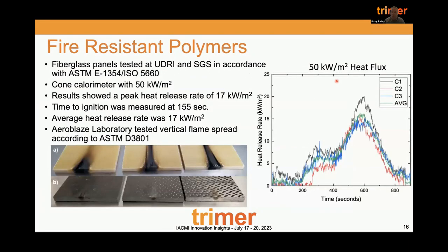If you look at more ASTM level testing, on the right, this is a 50 kilowatt per meter squared cone calorimetry test. It's an ASTM E1354 test. These values, this is with fiberglass, are extremely low. The green line is the average. And these are about a little over a third of what would be required for a Navy submarine. There's currently no material that'll meet that spec. So extremely good fire performance. And these are some vertical flame spreads showing essentially no flame spread, especially in the carbon.